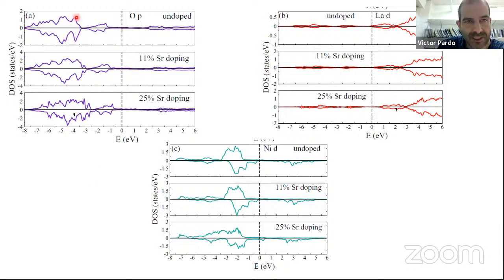Something else we noticed is that the density of states of the oxygen p bands changes when you start doping. Remember that I said at the beginning that one big difference between nickelates and cuprates is that in the undoped compound, the oxygen p bands are quite low in energy. They are far away from the Fermi level. But when you start doping with strontium, the oxygen p bands move towards the Fermi level.